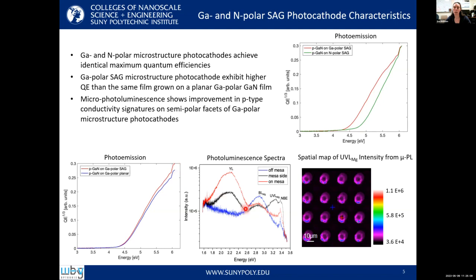And looking at micro-PL spectra, we can see that in the areas of the microstructure semipolar facets of the gallium polar sample, we see improved UVL efficiency in the photoluminescence, which is suggestive of high p-type conductivity in those areas.